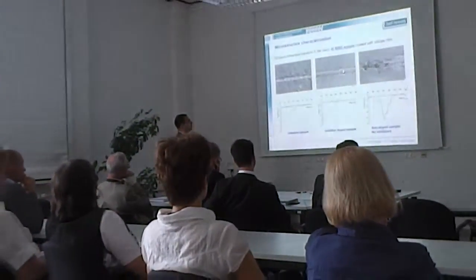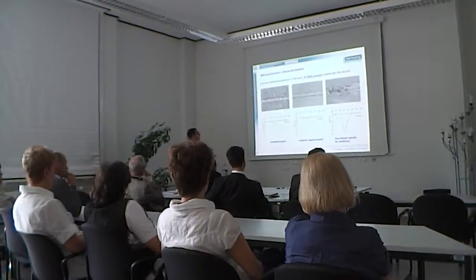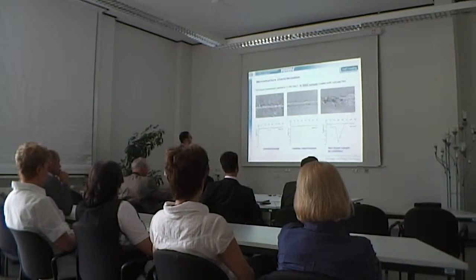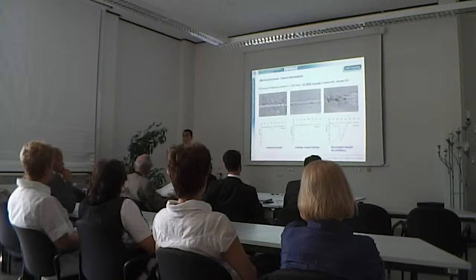Scanning electron microscope images of the surface of the defect showed this is the silica film, and this is the defect area, where the aluminum substrate is uncoated. After 700 hours in a 0.5 molar sodium chloride solution, in the case of the sample without corrosion inhibitors, the scratch area is completely destroyed, pitting corrosion can be seen, and the depth of the pitting corrosion can reach about 40 micrometers. In the case of corrosion inhibitors, a layer of corrosion inhibitors, or self-healing layer, is formed in the defect, which prevents the effect of the corrosive solution on the metal substrate. Also, it can be seen here that the cracks at the scratch edge also healed. It looks like when skin is wounded and healed.